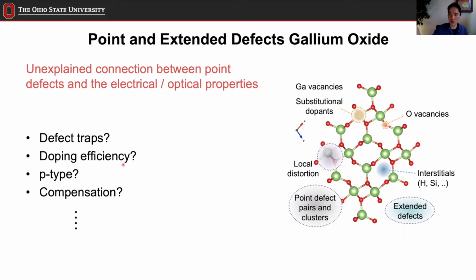You want to achieve this much doping concentration, but it's lower than that, right? And then you want to have N-type and P-type, but N-type is easy. In fact, it's automatic, but the P-type doping is pretty difficult, right? That means some kind of compensation. You dope the material, and then many of the dopants become compensated. So those are issues that exist. And all of these problems or issues that we don't understand revolve around the nature of the point defects within the atomic scale structure.